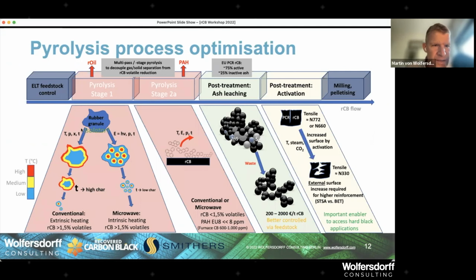As I said, the rubber granule is an isolator, and when we put energy in the type of normal pyrolysis, it's by temperature. We can actually put a vacuum, then things happen quicker, and by residence time, and also by surface area, so size of the granules. But we're heating from outside in, and that takes a long time. And typically, volatiles are higher than 1.5%. Whereas in the microwave, we're heating from the inside out, and the steel actually helps us because the steel is excited by the microwave radiation, and the carbon atoms are heated, and then it heats from the inside out, and the rubber is bursting because inside the rubber granules are already cooking and boiling, outside not yet. So that is much more destructive than the conventional pyrolysis.